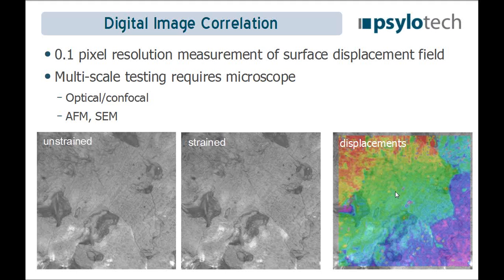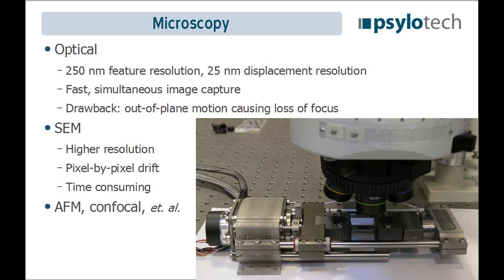Now, specific to the instrument and microscopy, one of the big values that we bring to the table with the instrument is under optical microscopes, if you have a little bit of out-of-plane motion, you lose focus, and then you can't use DIC. But optical microscopes have some huge advantages. For example, if you can get images down to the optical resolution of light, which is about 250 nanometers, so you can see features that are as small as 250 nanometers, and with DIC and the 0.1 pixel resolution that I mentioned before, you can actually see 25 nanometer resolution of the displacement field. So you can see those 250 nanometer features moving by as little as 25 nanometers.